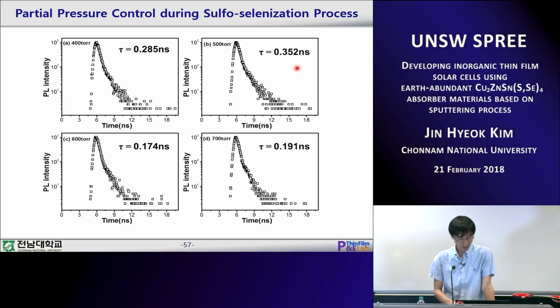efficiency result. Okay, so by controlling the sulfo-selenization process, I mean the initial pressure inside the chamber, we can change the cell efficiency. So we believe that there is a certain initial pressure for the sulfo-selenization process.